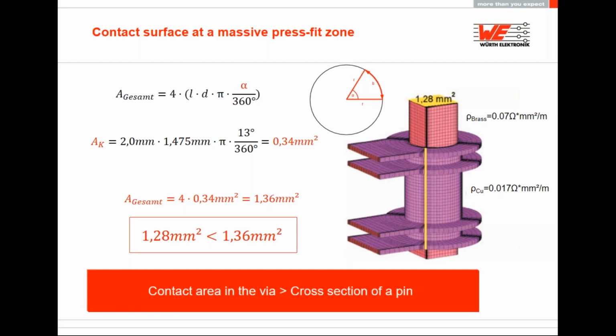So this is a proof of concept of the contact area for the PCB. One contact angle of one corner is an arc, so it's part of a circle line, and we calculate it with l times d times pi times alpha divided by 360 degrees. Additionally, we need the length of the connection area, which for a massive pin is the PCB thickness, called L in this case. Due to the fact that one pin has 4 corners, the factor 4 is added. This leads to the first formula on the first line.